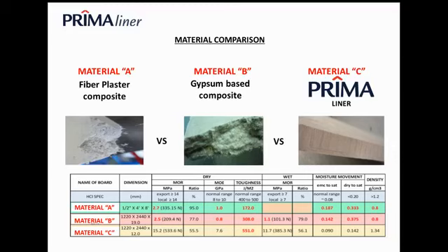For information, a fair test has been done in a lab to understand the differences in terms of performance of these three materials. As you can see on the table below, taking almost similar dimensions with a similar thickness for material A, B, and C, let's have a look at the strength performance. When it's dry, the MOR, or modulus of rupture, material A performs at 2.7 MPa, material B is 2.5, and material C is 15.2. So this is already almost 5 times stronger than material A and B.